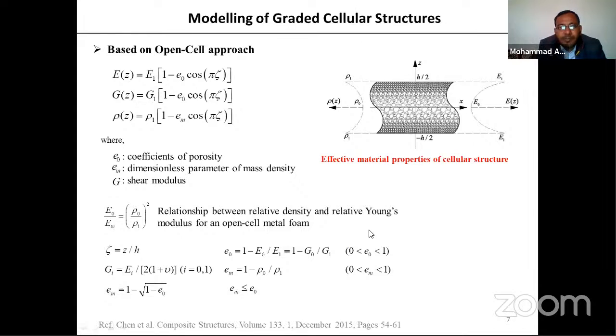Now we are discussing another kind of functionally graded structure, generally called a cellular structure. Based on the open cell approach, we have obtained the effective material properties, showing how the material properties vary along the thickness direction. From this figure we can also observe that the porosity, meaning maximum pores, is available at the center, and the top and bottom surfaces are generally less porous. So the effective material properties will obviously reduce maximum at the center.